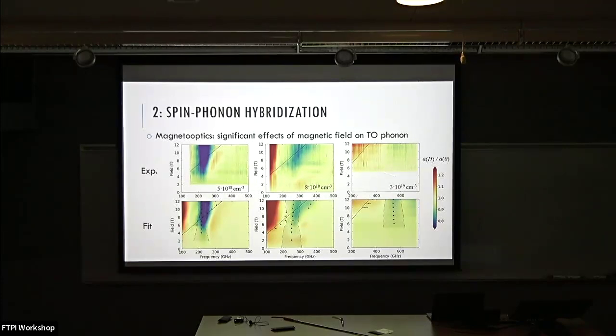There's more data. I'm not showing everything. And the main message is that definitely something happens. So what I'm plotting here is the magneto-optics coefficient. So this is the absorption in a field divided by absorption in zero field. So this is essentially 1 at zero field, and then something happens.